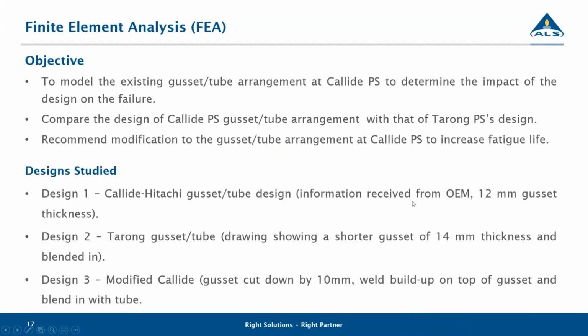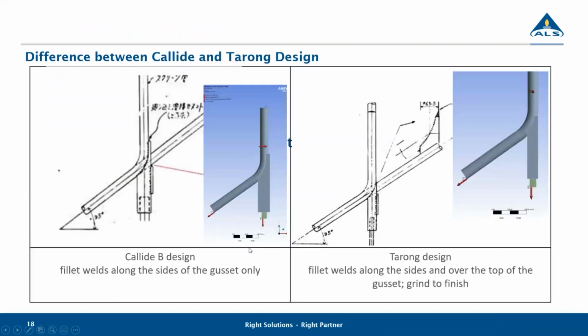The original design, which is a 12mm gusset, just welds on the side, no weld on the top. Then we looked at Tarong. It had a shorter gusset with a 14mm thickness, and it was blended in. And then we looked at a modified design to see what we can do with the existing geometry on site to see if we can improve that situation. That's a comparison between Callide and Tarong.